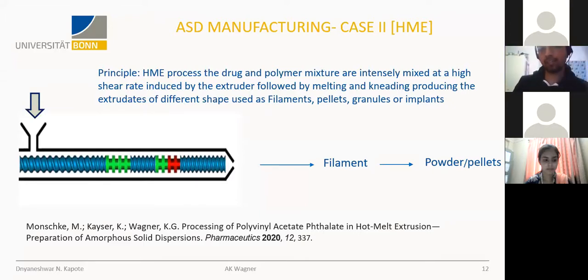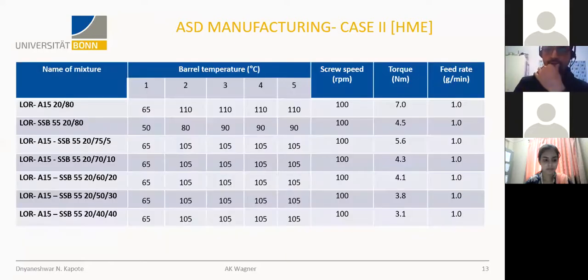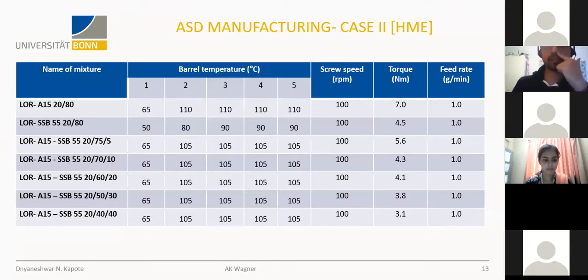So by this technique, you can also get an amorphous solid dispersion. The basic rule of hot melt extrusion is you have to analyze your sample and study it first for miscibility, and the second thing is the glass transition temperature. So the rule of thumb is you always extrude it at 50 degrees Celsius above the glass transition temperature of your mixture. So based on my glass transition temperature, which I determined initially for my physical mixtures, I tried to extrude it above 50 degrees Celsius. So we used a hot melt extruder from 3Tech, which is a 12 millimeter extruder.